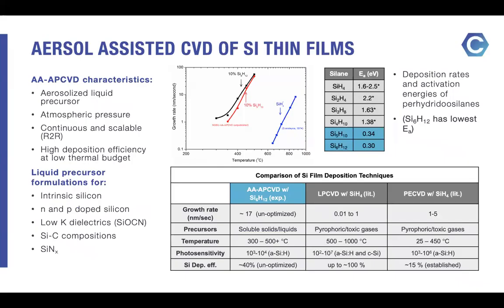So there was a technique developed several years ago called aerosol-assisted CVD. And so here, liquid precursor is aerosolized at atmospheric pressure. And so cyclohexasilane, cyclopentasilane, and monosilane were compared here. And we see that the growth rates, even at these low temperatures, are much higher with these cyclic silanes compared to monosilane. And this is primarily due to the low activation energy of deposition. So this method has been used to make both pure silicon, doped silicon, some silicon low-K dielectrics, silicon carbides, and silicon nitrides.